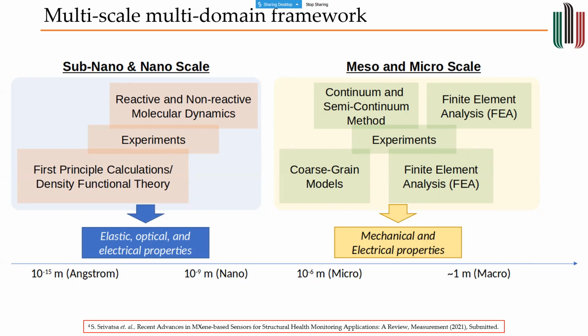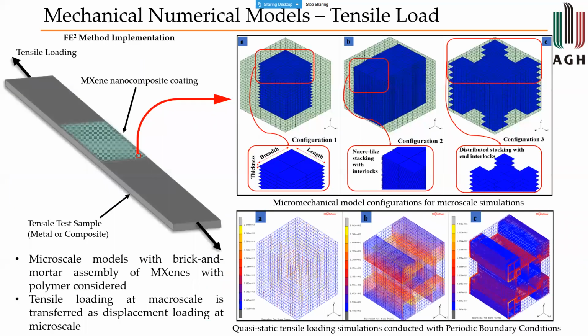So we did use an FE² method, where we are using the finite element method at two scales. And we assume a homogenized system where you would have periodic boundary conditions on the representative volume element that you have. This also comes from the empirical observations that we made from the experiments that we performed.